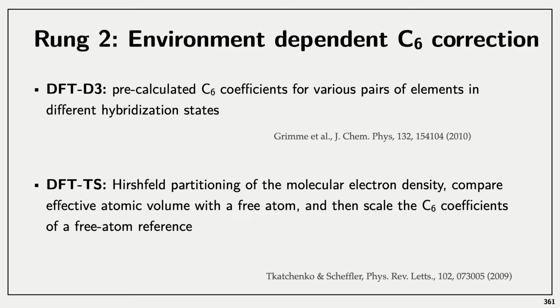And they do work very well, because that correction to the total energy also influences the relaxation of your system, right? Because you're trying to minimize the energy. So you are making sure that the van der Waals interaction is included in the relaxation of those geometries. So these are really good methods. Actually, they are not very expensive computationally compared to, let's say, a Kohn-Sham calculation. They are very inexpensive, typically done on top of PBE.